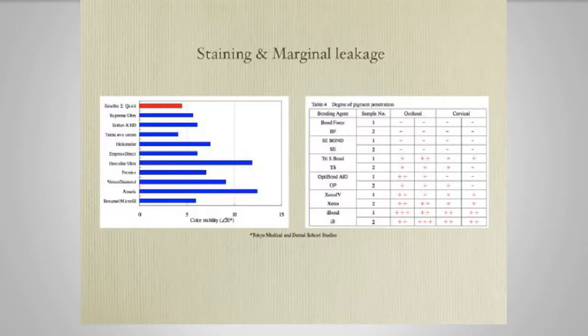A couple of studies on staining and marginal leakage here. The left is a staining study. Composites in the mouth are basically going to break down over time, and that's typically due to food and drinks that are put in the mouth. Now, in this study, they took various composite materials and cured them, and they placed them in coffee at about 80 degrees Celsius, and let them soak for about 24 hours. Then they measured how much of a shade change took place. So the left side there shows color stability of the material before and after that particular test. On the right side is a microleakage study that was done on human molars.